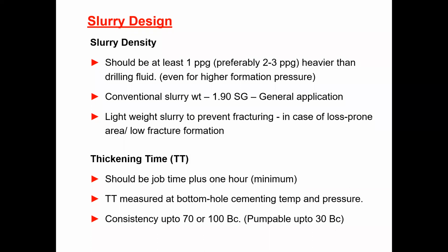Okay, as I explained now, in an inclined well, if there is some free water, then even at 1.4%, the top layer will be water. So you will not get zonal isolation. Gas or oil can pass through that. So our basic purpose of cementation is defeated. You got it? Yes, sir. Thank you.